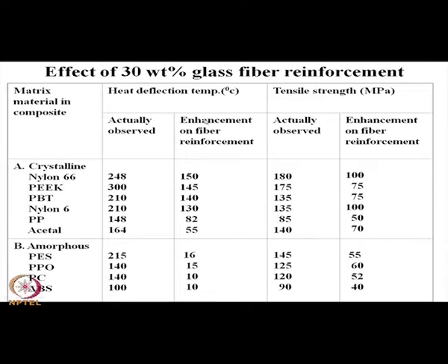Now, after incorporation of 30 wt% glass fiber in those matrix resins, it has been found there is an enhancement of heat deflection temperature by 150 degree Celsius if nylon 6,6 was the matrix. In case of PEEK, it was a 145 degree enhancement, whereas in case of polypropylene, it is quite low. For acetal, it is quite low.